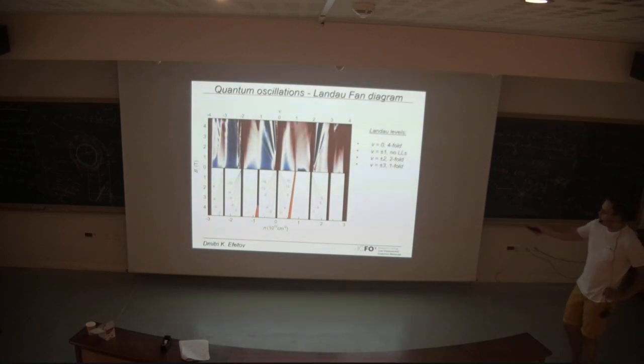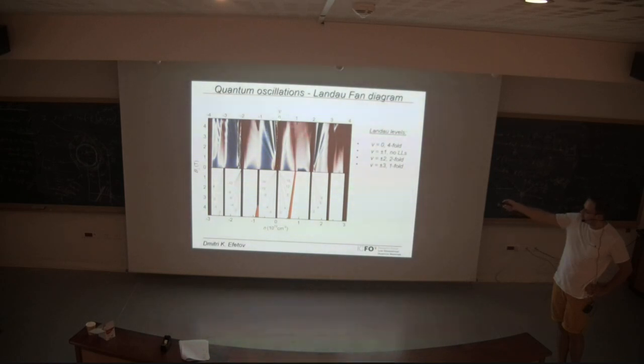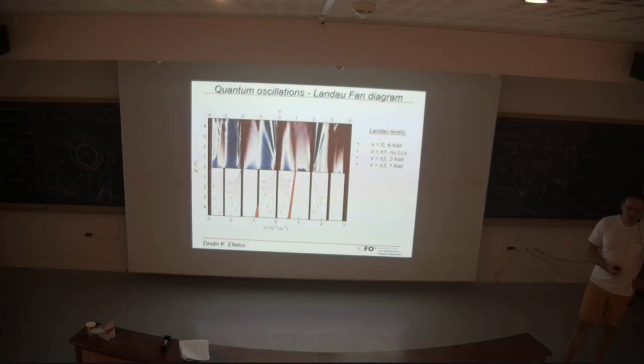So if we start with the Fermi surface at 1/2 here, so this is the charge neutrality point, we observe Landau levels fanning out to the left side and the right side, and if we closely analyze the slope of these Landau levels, we can show that all of them are fourfold degenerate. These are just lines which we retraced here. As you can see, all the Landau levels from the charge neutrality point are +4, -8, -12, -16. So they have a fourfold degeneracy, and therefore, again, valley and spin of the underlying ground state are conserved.